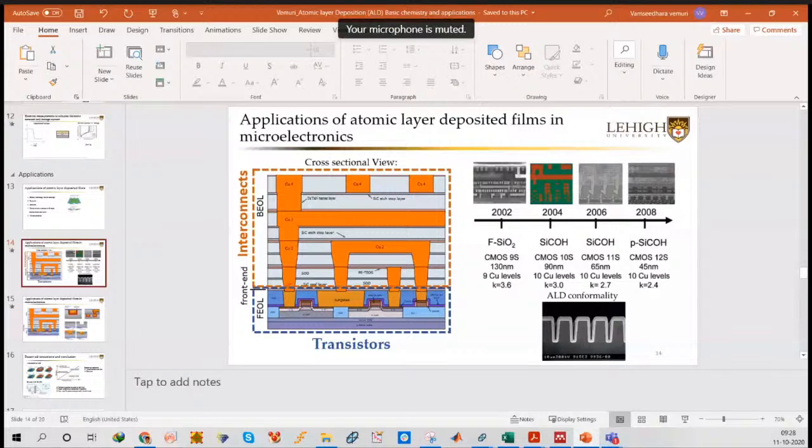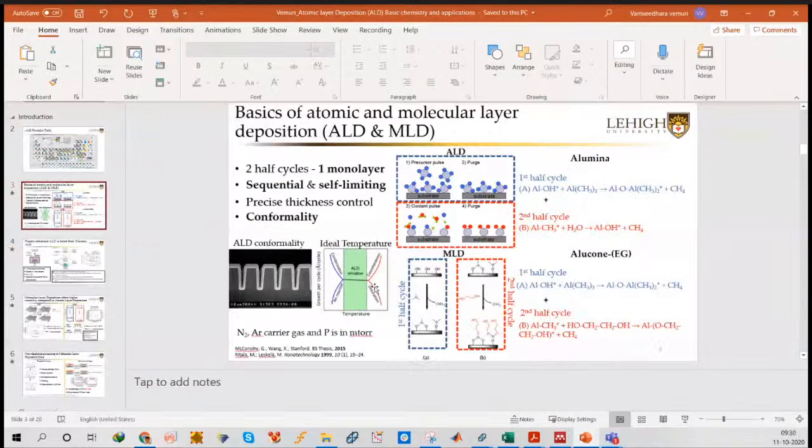Yes, yes. So you cannot cross this temperature window. If you go too high, you decompose the precursors that are deposited, or sometimes you dissolve. So you get only amorphous films by using thermal ALD. But in the case of plasma ALD, since the ions impinge and give some extra energy to the substrate, you can get polycrystalline and in some cases crystalline films as well.